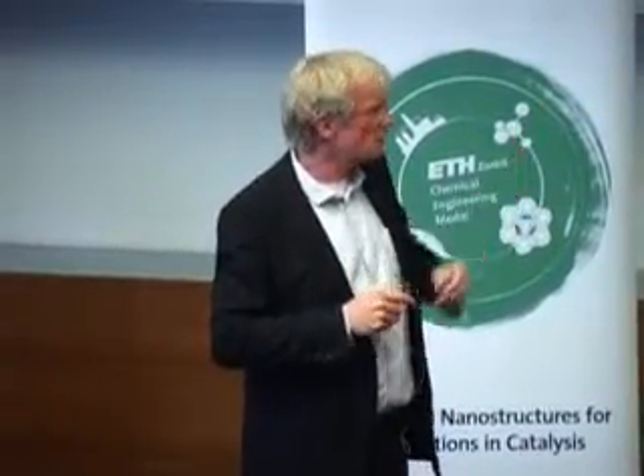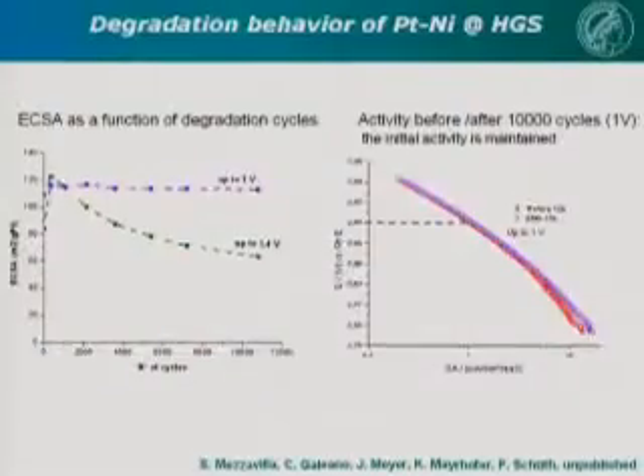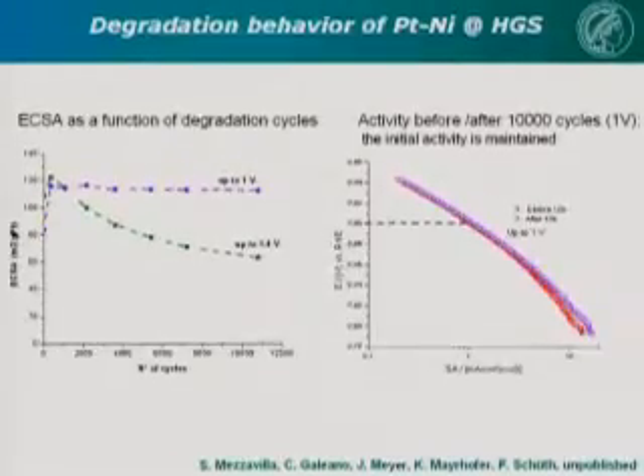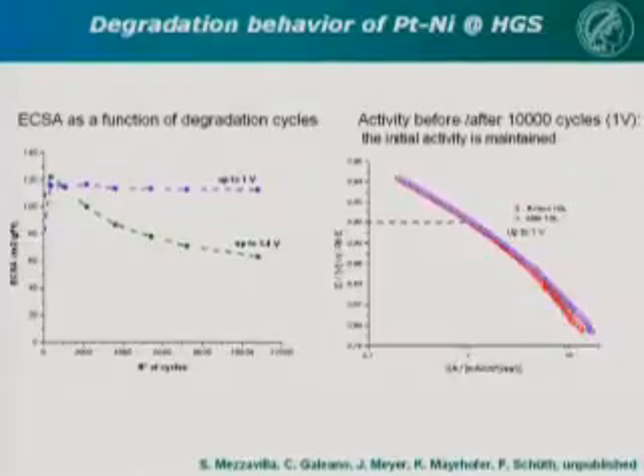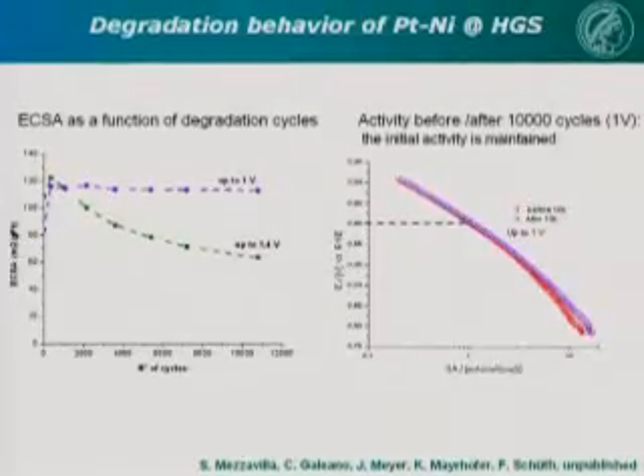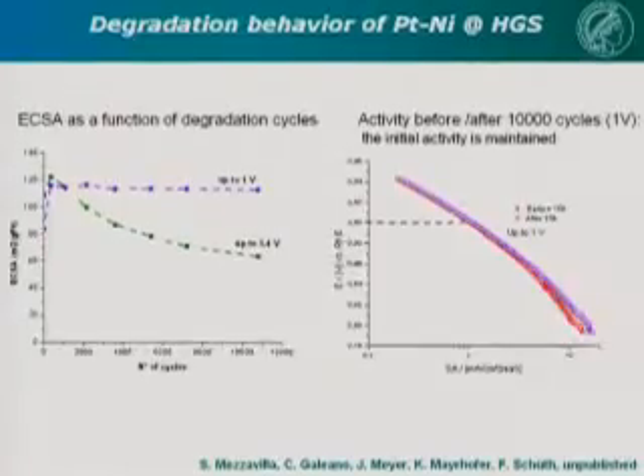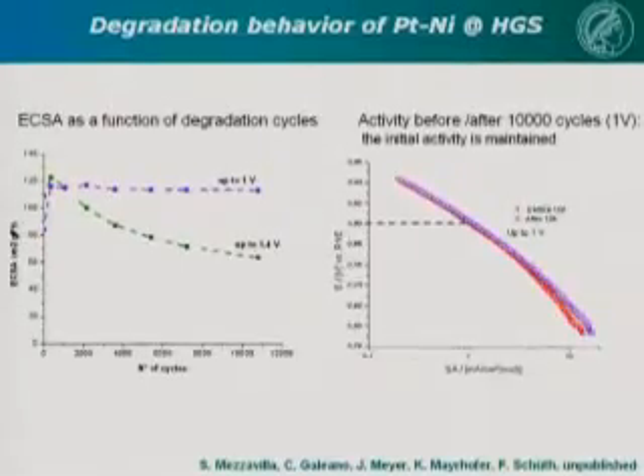So we are really excited about this work and the stability. Yes, stability of these catalysts is approximately the same as for the confined platinum particles in the hollow graphitic shells. If we cycle to very harsh conditions up to 1.4 volts, if we only do the cycling to 1 volt, which is the normal operation range, activity is basically stable over 10,000 cycles. But in a real-world fuel cell, you have start-stop situations with ill-defined conditions, then you can have potential excursions, and so this is something to worry about to some extent.